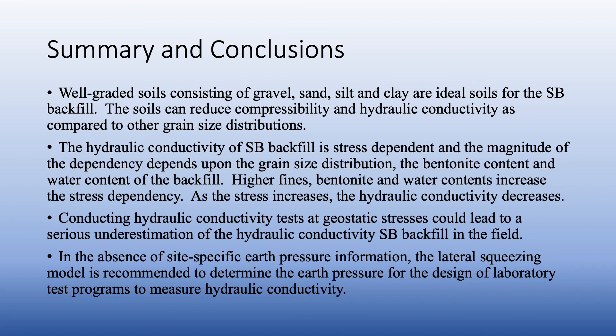In summary, well-graded soils consisting of gravel, sand, silt, and clay are the ideal soils for soil bentonite backfill, as they reduce compressibility and hydraulic conductivity compared to more uniform grain size distributions. The hydraulic conductivity of the backfill is stress-dependent, and the magnitude of that dependency depends on grain size distribution, bentonite content, and water content. Higher fines content, higher bentonite content, and higher water content all increase stress dependency. As stress increases, hydraulic conductivity decreases.